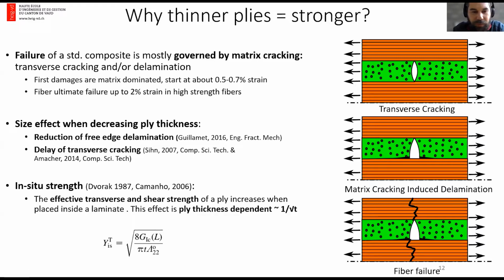where it was proposed to consider that the transverse strength of a ply is not an intrinsic property, but it is an in-situ property. It depends on the neighboring ply. Indeed, the strength of a ply is governed by the nucleation and propagation of a transverse crack, like you see here. And this transverse crack is pinned at the two extremities by the neighboring plies.